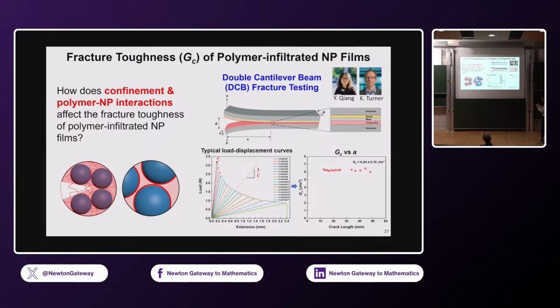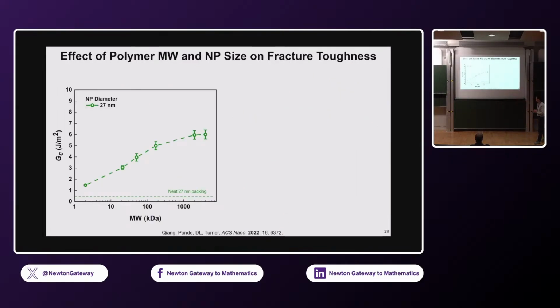The way this is done is that we propagate the crack a little bit and then we let it go. So there's a load, and then we let it go, and we do it repeatedly, okay? So the crack propagation is pretty stable. And from this load displacement curve, we can get this G sub C, which is the fracture toughness data. Okay, it's very reliable, but very tricky experiments. Eway was just a master at doing this. All right, so let me first talk about the confinement effect.